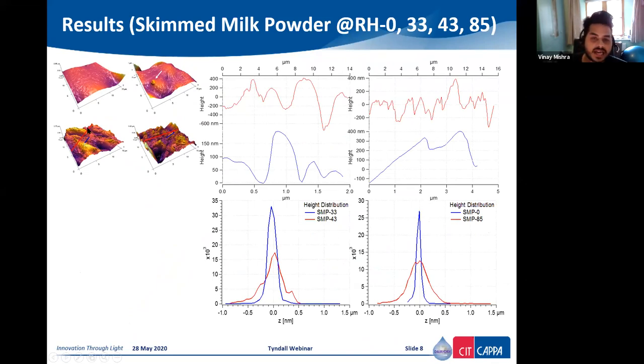Now, the red line on skim milk powder 43 and the blue line on the 3D topography on SMP 43, I'm trying to show their orthographic projection on the whole image and one single lactose crystal. So this is skim milk powder at a relative humidity 43. You can see the brain-like structure or the waviness on the surface of skim milk powder, where one small lactose crystal was approximately 160 nanometers and 1 micron in size. Now, with increase in the moisture absorption, you can see there is less waviness because there are uniform higher crystal structures of lactose everywhere, where the lactose single crystal has increased to a size of 4 micron.